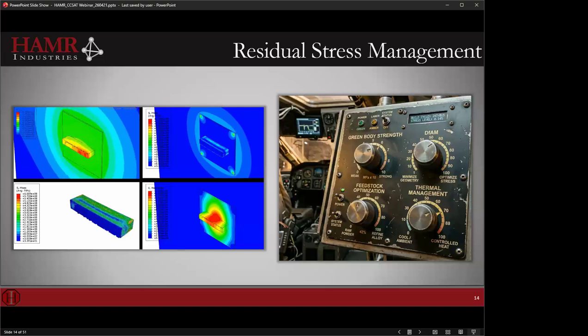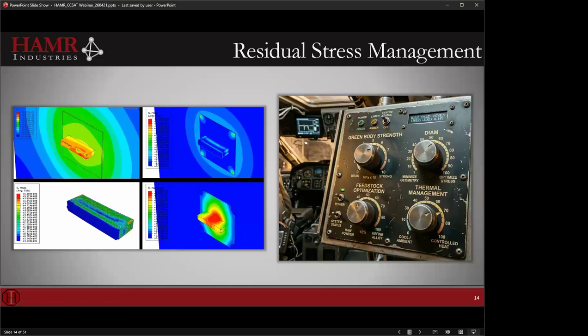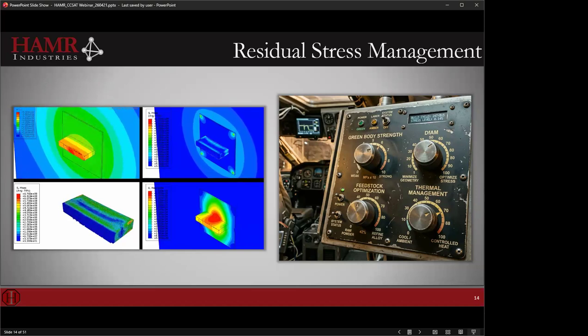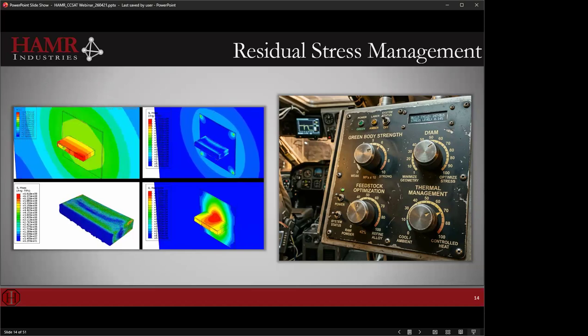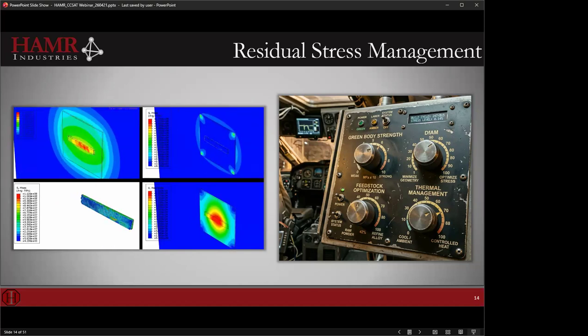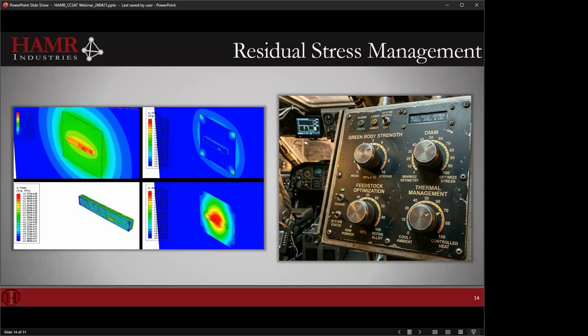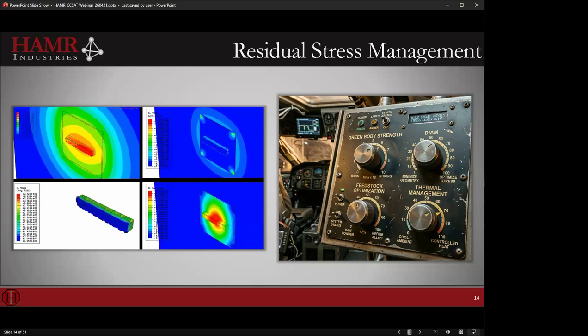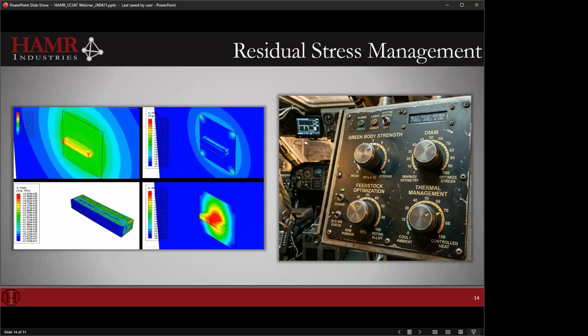And then thermal management. So most of these stresses are thermally driven. If we simulate it, we see that in simulation and we see that in practice. So the same material, different geometries, we know they have the same amount of stress from peening because we process them at the same conditions. We see some things crack and some don't, and it's primarily thermally driven.